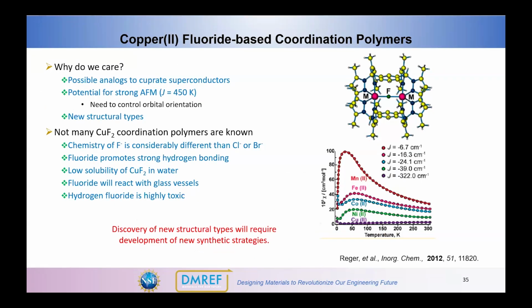I'm not going to have time to go into this in as much detail as I'd hoped, but again, we had worked in the area of looking at copper fluoride coordination polymers, as possibly being analogs to cuprate superconductors with strong magnetic exchange through the bridging fluoride in between copper type systems. And there's a lot of chemical challenges in these materials because the fluoride acts considerably different in many ways than what chloride or bromide does. It promotes strong hydrogen bonding, has low solubility in water. Fluoride will interact with your glass vessels, and it provides various issues with respect to toxicity and other things. So there are complications there chemically, but I think a lot of potential.